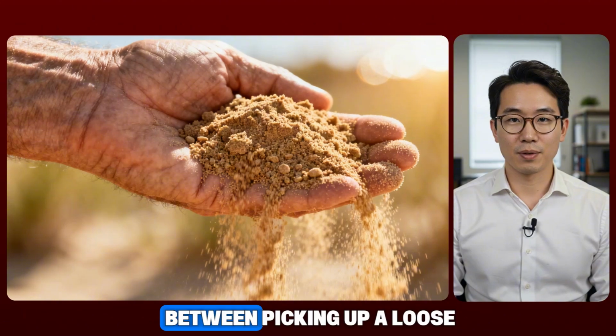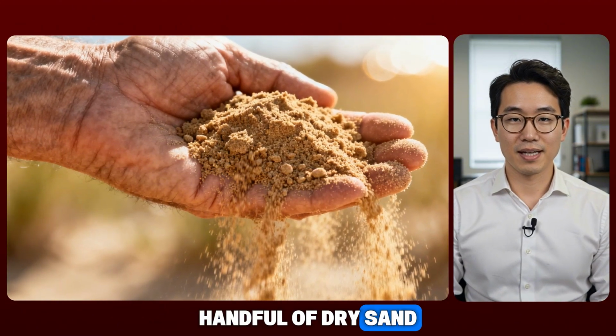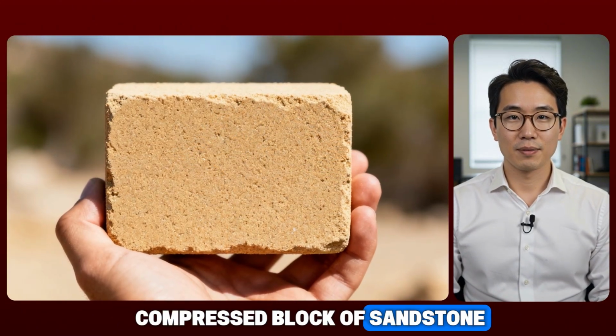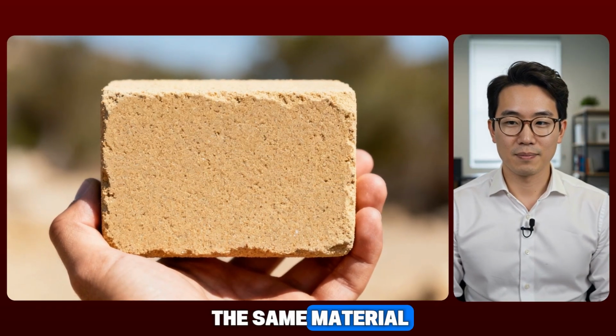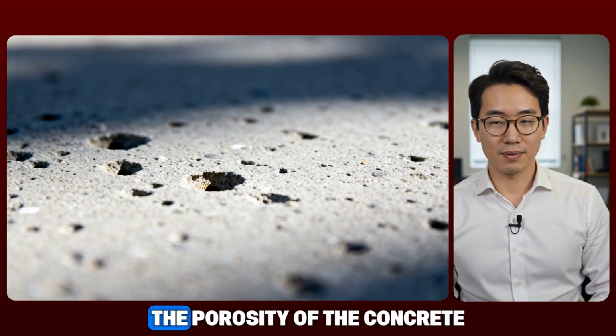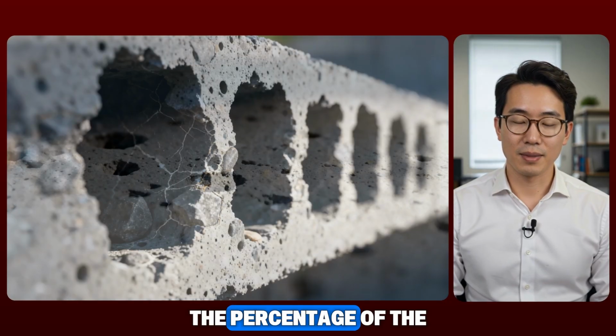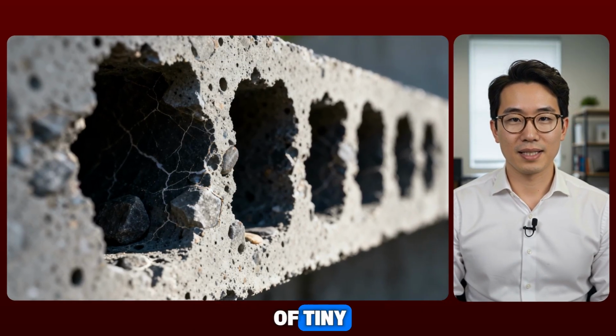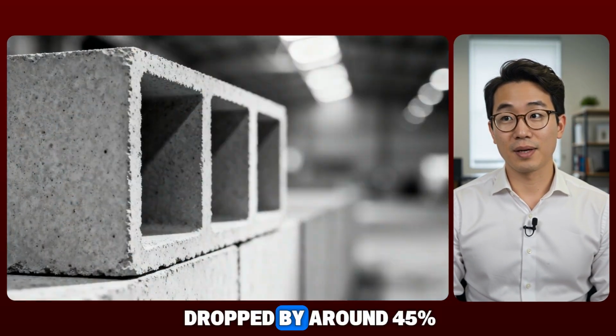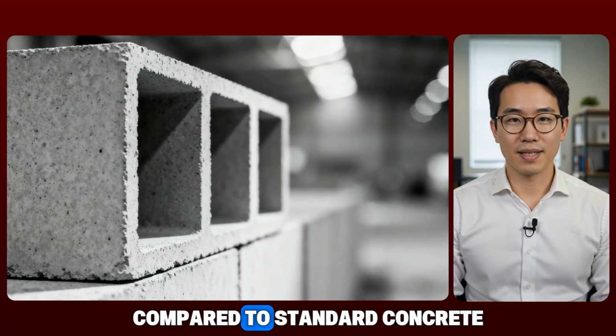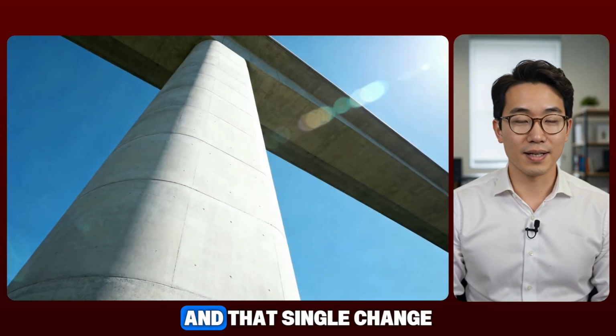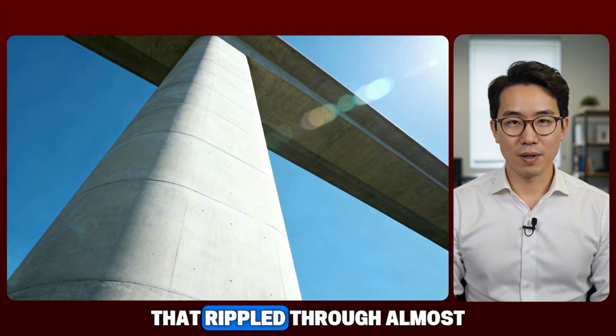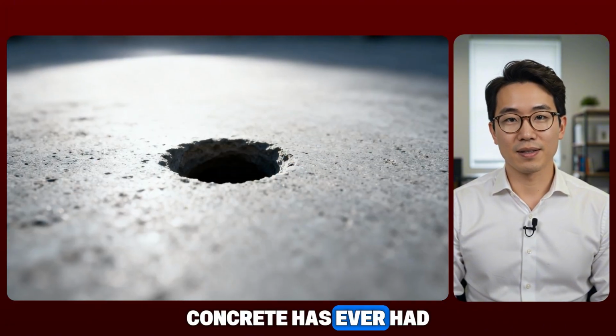Think about the difference between picking up a loose handful of dry sand and picking up a compressed block of sandstone. Both are made of the same material, but the structure is completely different. The porosity of the concrete, the percentage of the total volume made up of tiny internal gaps and voids, dropped by around 45% compared to standard concrete made the same way. And that single change had consequences that rippled through almost every weakness concrete has ever had.